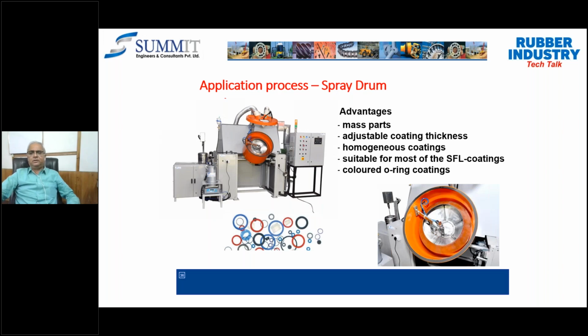Especially there are certain components which are coated beyond 50 microns also. The best example is our food grade industry application, our tawa, the frying pans, which are coated with PTFE. It has around 50 to 60 microns of coating thickness. The behavior and the process requirements are different for that, right? I deliberately try to explain the behavior part of it. Now, for coating a rubber and for coating a frying pan, you will require different procedures, right? So it could be the immersion or dipping coating technique, it could be the spraying technique, or it could be the brushing. Okay, but I would not recommend going for the brushing.